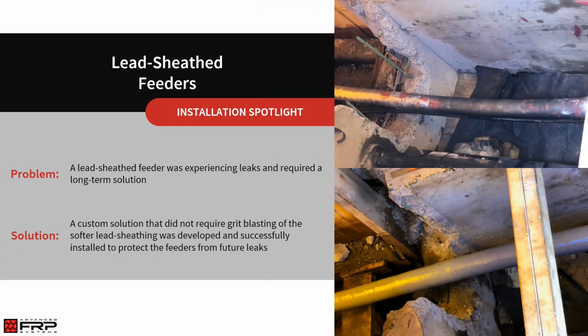We also ran into an issue where a lead sheath feeder was leaking. These are lower pressure feeder technologies, but the lead sheath is much softer than a standard carbon steel pipe. So grit blasting was not feasible. So we validated an alternate surface preparation method for the adhesion zones on this lead sheath feeder. And we were able to design a custom solution that protected the lead sheath feeder, prevented any leaks, and adhered to the surface with over 2000 psi of adhesion. Also, we needed to make sure we didn't create a stress point at the end of the carbon fiber. So we had to taper that carbon fiber down so that there wasn't a stiff point right at the end.